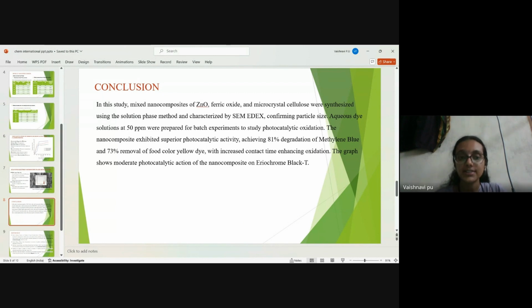And the conclusion is that in this study, a mixed nanocomposite of ZnO, ferric oxide, and microcrystalline cellulose was synthesized using the solution phase method and characterized by SEM-EDX confirming particle size. Aqueous dye solutions at 50 ppm were prepared for batch experiments to study the photocatalytic oxidation. The nanocomposite exhibited superior photocatalytic activity, achieving 81% degradation of methylene blue and 73% removal of the food color yellow dye with increased contact time, enhancing the oxidation. The graph showed moderate photocatalytic action of the nanocomposite on Eriochrome Black-T.